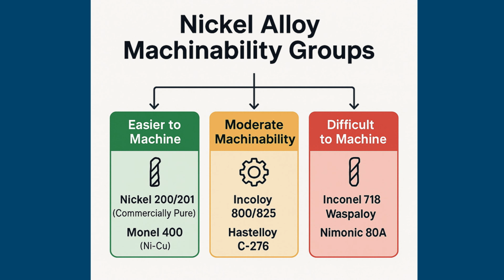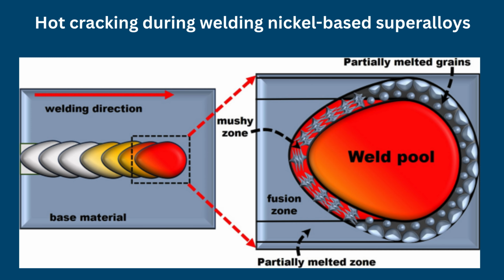Nickel-based superalloys, for example, are difficult to machine because of their high strength, low thermal conductivity, work hardening, and tendency to generate substantial cutting temperatures. Welding can also be challenging because precipitation-strengthened alloys are susceptible to heat-affected zone liquation and hot cracking. These limitations motivate continued development of advanced joining, machining, coating, repair, powder processing, and additive manufacturing technologies.